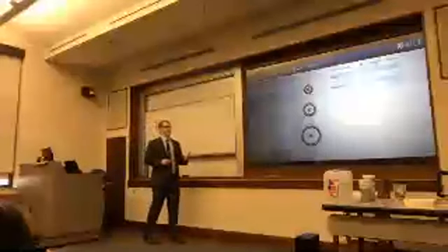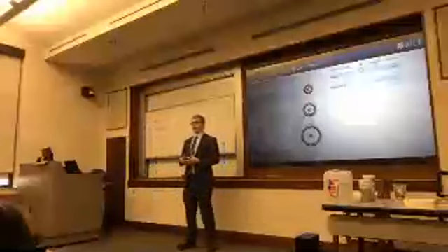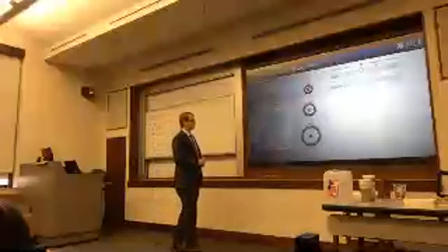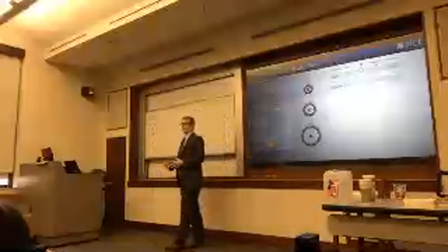In fact, if we look in the literature, we can find that graphene in chlorosulfonic acid has a shift of 33 wave numbers. And of course, graphene is being protonated by the top and bottom surfaces, increasing the G peak shift. So we think the reason that this material shifts by 37 wave numbers is because it's being protonated by the internal and external surfaces.